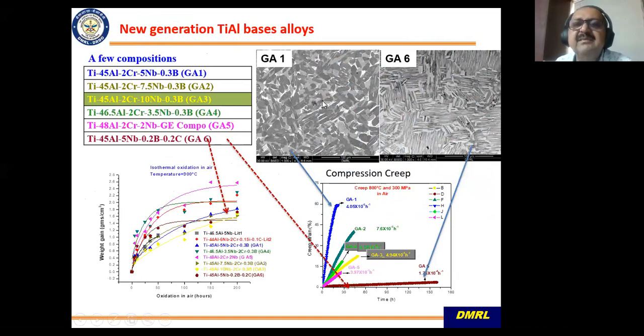And again, it's a very complex phase structure. You have at least 3 phases: the bright beta phase, and then you have the gamma phase, which is gray, and the slightly less dark alpha phase. So there are at least 3 phases which are there, if not more. It's a complex kind of phase diagram, and also the microstructures are slightly complex.